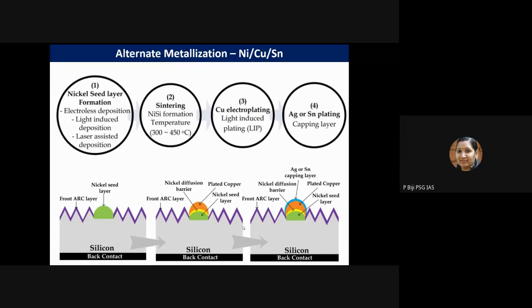Because you need direct contact between the metal and your emitter layer, a nickel seed layer will be deposited in these openings of the ARC layer as per your design pattern. Then your sintering happens, and then the copper will be electroplated over the nickel seed layer. After that, your capping layer, like a silver or tin capping layer, can be deposited. So that's basically the metallization steps involved in this particular alternative metallization.